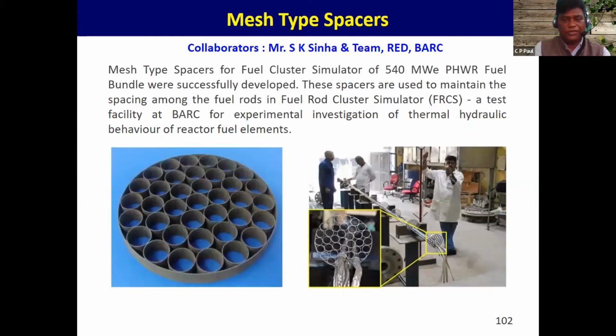Another beautiful example: we took up our program in building mesh type spacers for fuel cluster simulators for PHWR, pressurized heavy water reactors, 540 megawatt electric. This particular component you are seeing, BARC was trying to develop for the simulators. It has a very nice diamond structure, some triangular structure and circle. The wall thickness is around 0.5 millimeter, and the dimensional accuracy they are asking for is about 100 micron. This will be used as a spacer to keep the heating tubes separated during the assembly.